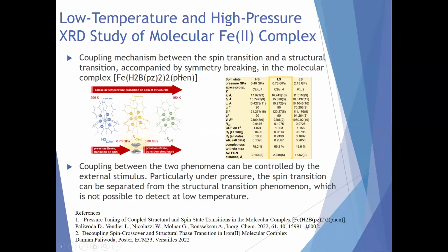So here is an example of an X-ray diffraction study of a single crystal under high pressure and low temperature that we carried out on a molecular iron(II) complex. Thanks to this study, we were able to highlight a coupling mechanism between the spin transition and a structural transition, accompanied by a break of symmetry in the molecular complex. It was shown that the coupling between the two phenomena can be controlled by the external stimulus. Particularly under pressure, the spin transition can be separated from the structural transition, which is not possible to detect at low temperature.